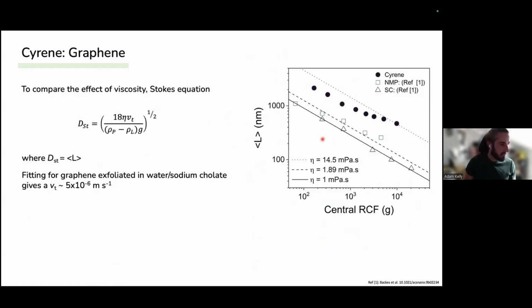So to investigate this a little bit further, we can use the Stokes equation, which is for particles moving in viscous media. In this case, we're going to relate the Stokes diameter to the average nanosheet length. So I've taken some data from this reference down here, Backes et al., for graphene exfoliated in sodium cholate and also graphene exfoliated in NMP. And what we find is that these triangles here, with a viscosity of 1 for water, sodium cholate, you find good agreement with a terminal velocity of 5 by 10 to the minus 6.